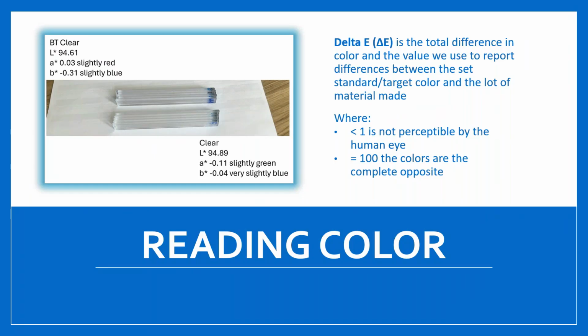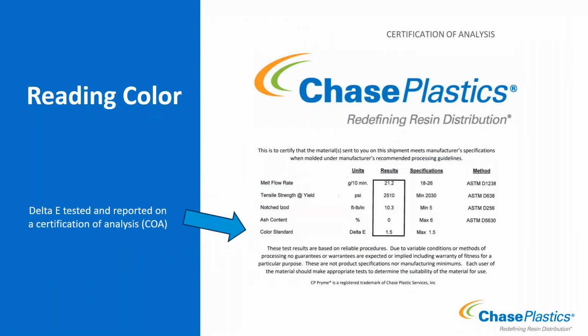And so an example of that would be here. In cases where color is important and it had been matched and we have to hit a certain color standard, what you might find is on the certification of analysis, C of A, that you receive with all of your lots of material to go over the testing that was done for that lot to show how it performs, you might find the color standard testing on it. In this particular case, this is a reprocessed material that's black, and you can see the color standard delta E, the specification or the max range for this particular one that's allowed is 1.5. And so a little bit over the 1. So if you have the target and then you get all the way to a 1.5, you might be able to see a slight difference because it is over that 1. But you can see on a cert, this is what it looks like. Delta E value is reported after being tested on here to compare. And so a great way to show our color difference here.